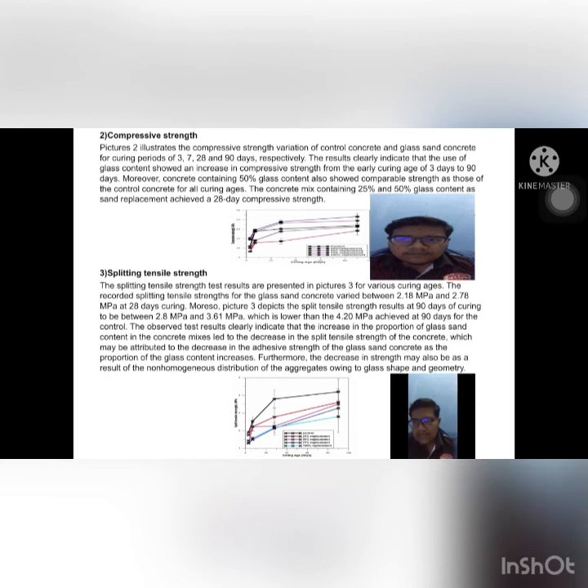The observed test results clearly indicate that the increase in the proportion of glass sand content in the concrete mix leads to a decrease in the split tensile strength of the concrete, which may be attributed to the decrease in the adhesive strength of the glass sand concrete as the proportion of glass content increases. Furthermore, the decrease in strength may also be a result of the non-homogeneous distribution of the aggregate owing to glass shape and geometry.